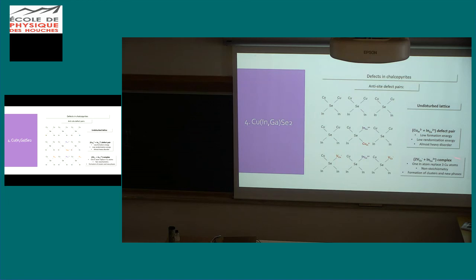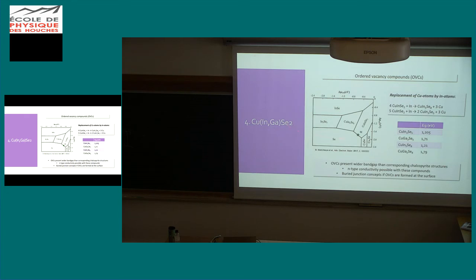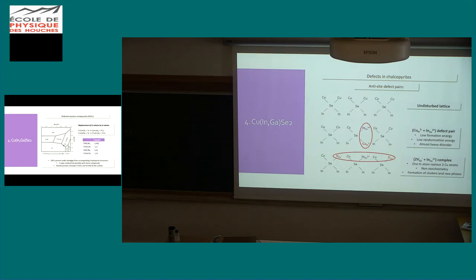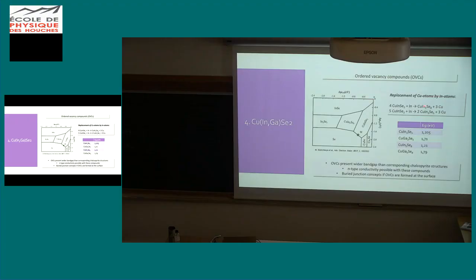And you can have this kind of periodic complexes with two copper vacancies and one copper-on-indium antisite. Then you create a complex like this that are non-stoichiometric defects and can form clusters of new different phases. And this is the case if you take a look at the formation diagram of all these possible compounds. Basically, forming this type of cluster and propagating them, we can have new types of compounds like CuIn5Se8, CuIn3Se5. So this means if we add one atom, we don't have 33% more complexity. We really have an order of magnitude more complexity in this material.